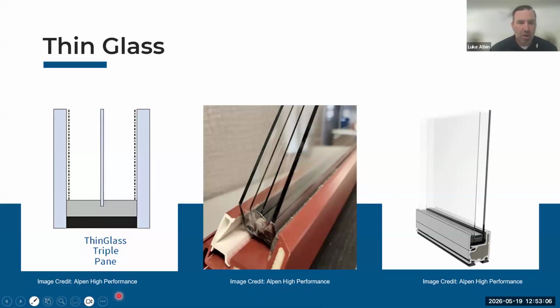Then last, we have thin glass. So thin glass is pretty unique in that instead of using that conventional triple pane system, a piece of thin glass is used. Where does the thin glass come from? Well, it's the same glass that is on your smartphones and flat screen TVs, half a millimeter to 1.3 millimeters typically, instead of the 3 millimeters where traditional glazing starts off. So you still get all the benefits, and they found that you don't need that thick piece of glass to have the same thermal performance as a conventional triple. That convection loop is still broken up by the piece of thin glass.